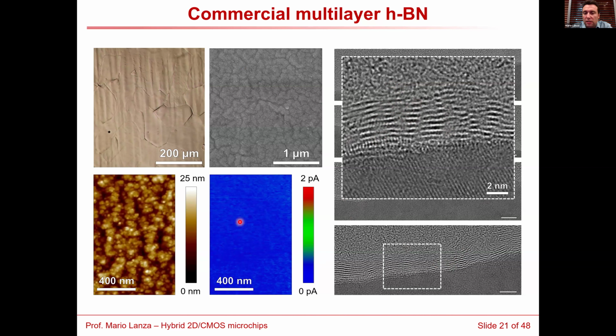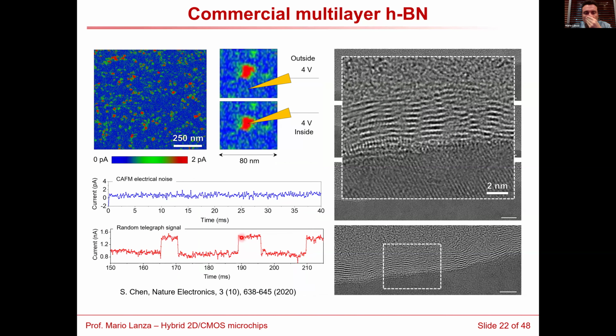We repeat the conductive AFM scans, but now we apply a higher electrical field. And what we observe is a picture like this. We observe many locations that are insulating and show no current. However, we also observe some isolated conductive spots. Because we apply the same voltage to the whole image, these are basically electrically weak locations.